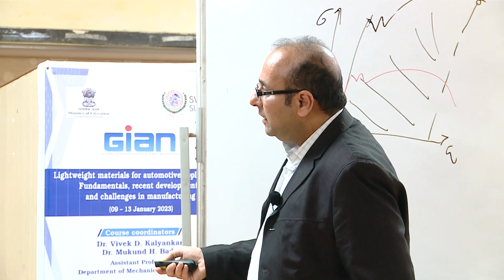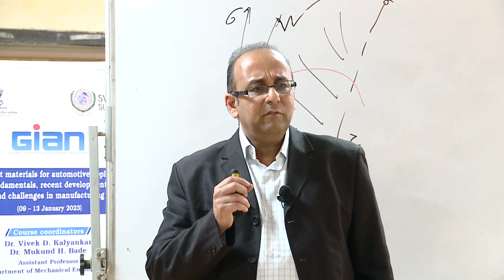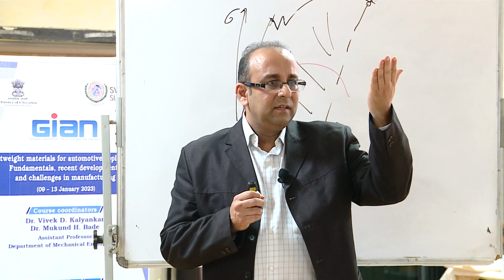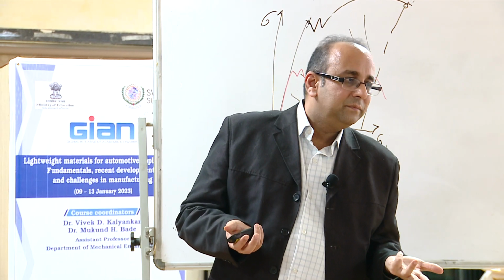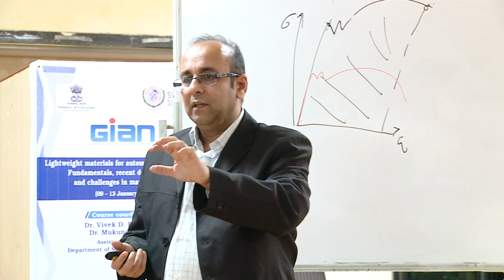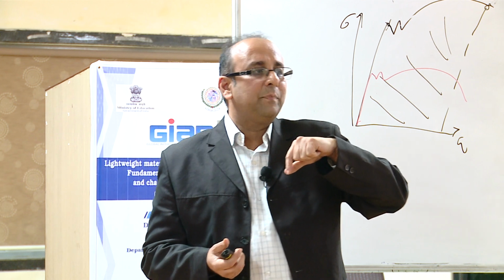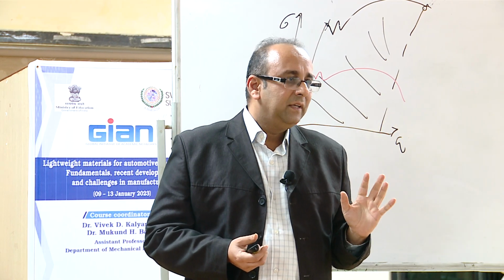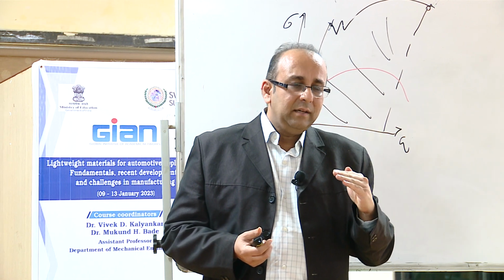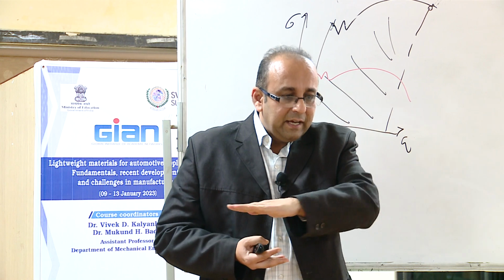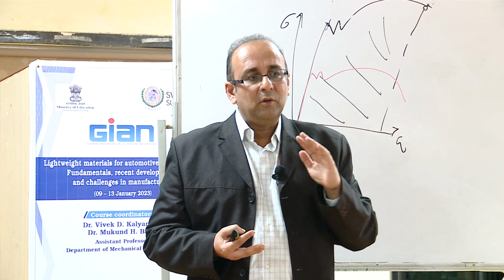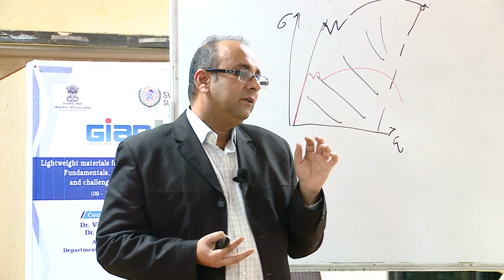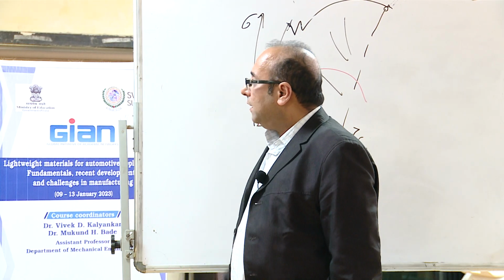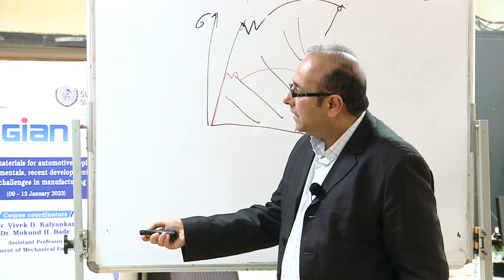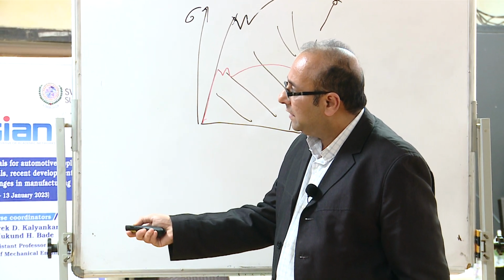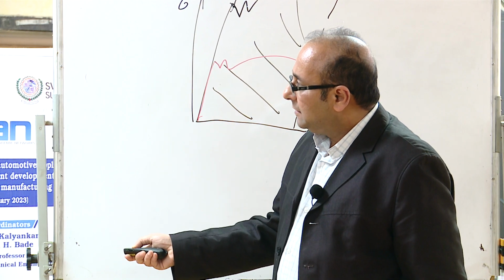This material has an added advantage that it has a coating on it. Normally what happens is that if you raise it to 700 degrees centigrade and again cool it, your zinc coating will anyway not work. It will evaporate. If I don't give the coating, the steel will corrode. That's why there is a separate coating which is necessary, which you call aluminum silicon coating, and that is applied on this Usibor material. And this coating basically does not evaporate, it melts at this temperature and spreads uniformly throughout the part. And it remains on that. And this coating is important to give corrosion protection to this steel. So now this banana diagram we have invented, we realized that we could maybe have had the same thing if we would have been in 1900. This is the material, press hardening material.